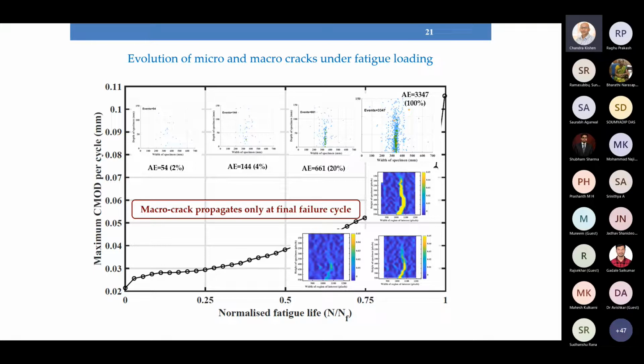And what we see here is only the small dots, the events of low energy. But in the next stage, from 50% to 75% of the life, we see the acoustic emission events increasing. So it has gone up to 20%. But in the final 25% of its life, 80% of the micro cracks have formed.